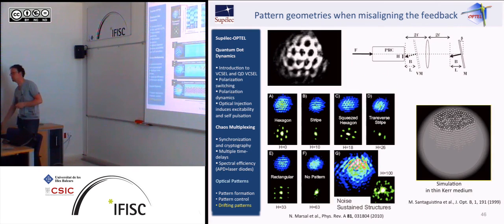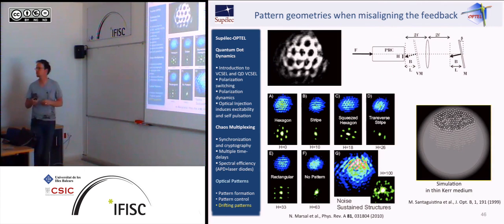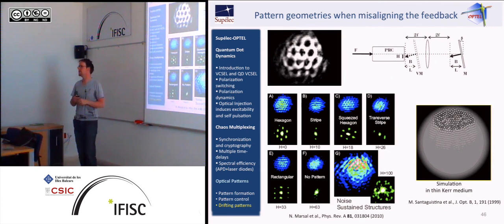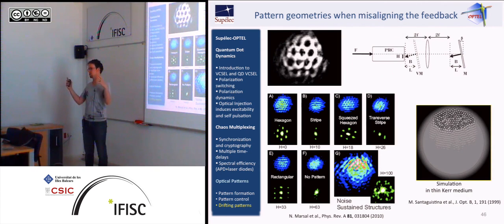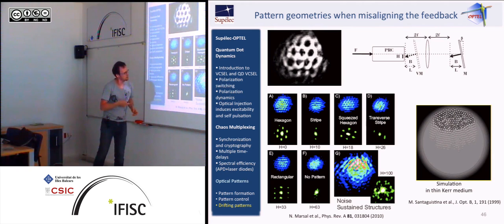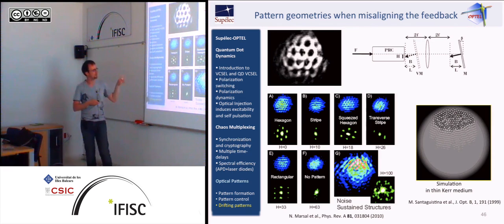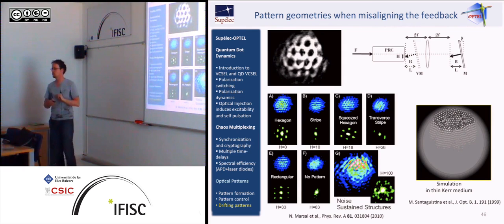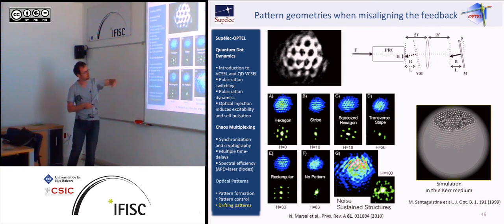Is the region where the dots are, where you still have an overlap from the feedback? Yeah, we still have an overlap. It's weak. I mean, the region where the forward and the backward beam are overlapping is weak. So it means also most probably that we have stripe dynamics in a very small region of the pumping beam. But we are feeling a convective kind of instability, but we see indeed these spots appearing, they are competing strongly. I mean, I have transverse cuts that I could show you with five or six peaks that are just spiking up, spiking back.